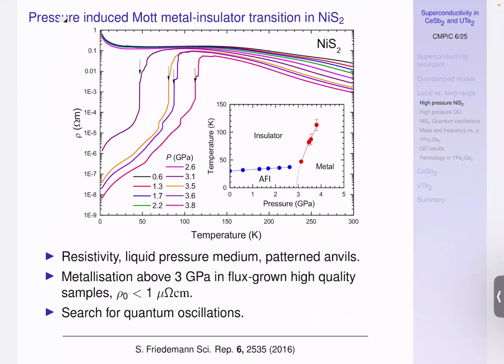Nickel disulfide is insulating at zero pressure. Resistivity versus temperature turns up here at low temperatures, but as you increase pressure, you don't need much pressure to turn it into a metal. The insulator to metal transition is at about 3 gigapascal, which is 30 kilobar. And what was really important, and that basically motivated this work, was that we could see that the residual resistivity is as low as about 1 micro-ohm centimeter. So you can make ultra clean nickel disulfide single crystals using tellurium flux, which are pure enough that you should be able to see quantum oscillations.